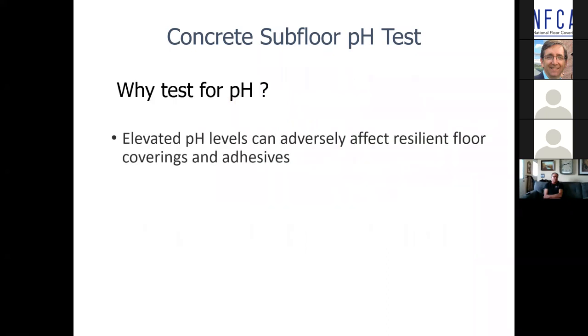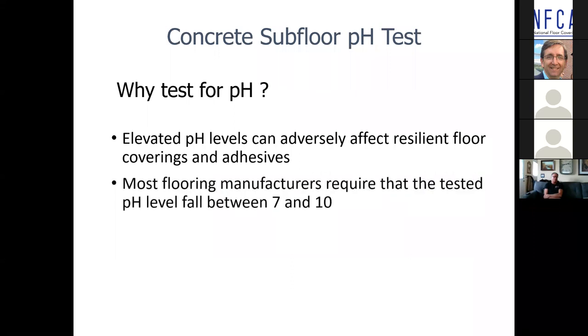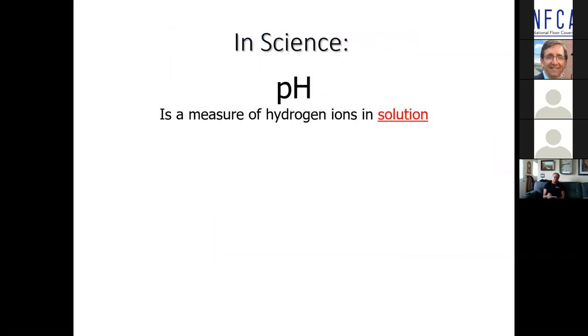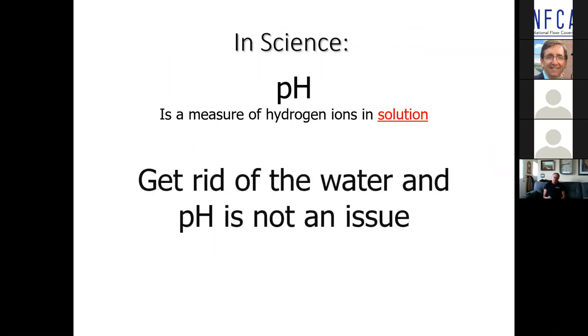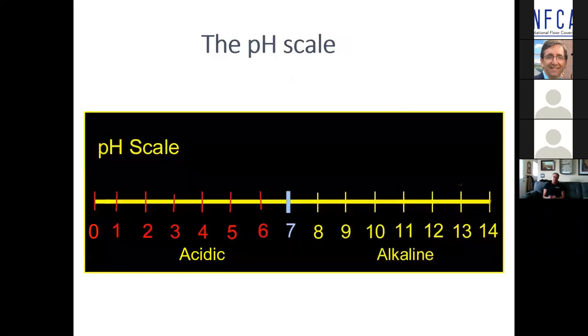Okay, why test? Well, we test because there's no question that a high pH solution can break down adhesives and lead to flooring problems. No question about it. Most flooring manufacturers still require that it fall between 7 and 10. It's a measure of hydronium, hydrogen ions in solution. The point of that is if there's not enough moisture to create a solution, pH is not an issue. If I take that pH strip and put it on the top of my desk and don't add water, I have no pH at all. If I put it on a concrete slab and I don't add water, there's no pH.